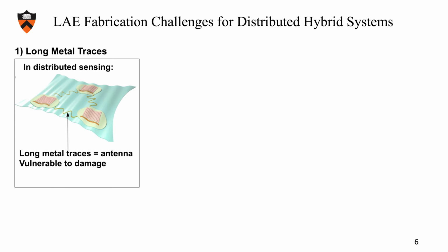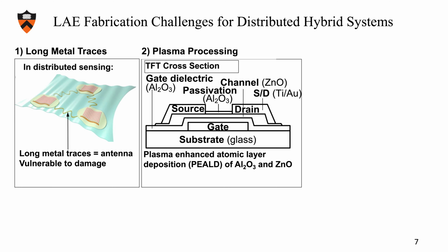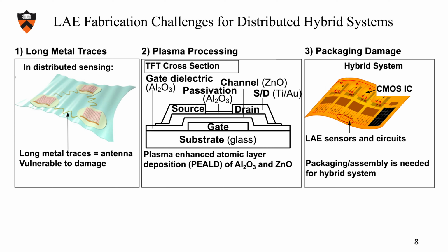The second one is plasma processing. From the TFT cross-section we put here, we can see that the aluminum oxide, zinc oxide, and aluminum oxide are dielectric, channel, and passivation. They are all deposited with plasma-enhanced atomic layer deposition. The plasma could cause damage. The last one is packaging and assembly damage because we are making hybrid systems.